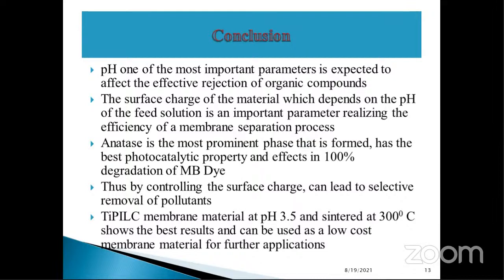And also, the titanium pillared clay membrane material, which has been synthesized at pH 3.5 and sintered at 300 degrees centigrade, shows the best results and can be used as a low-cost membrane material for further applications if we compare it with the values of the alumina membrane.